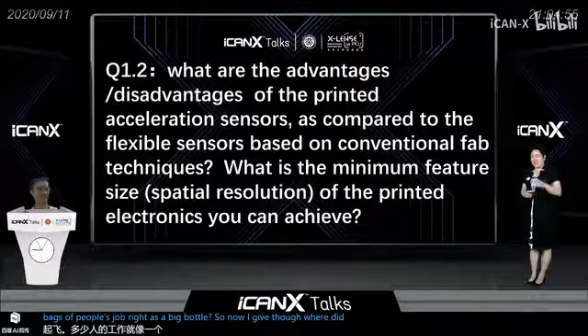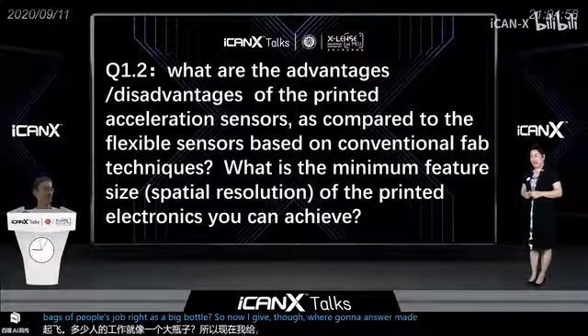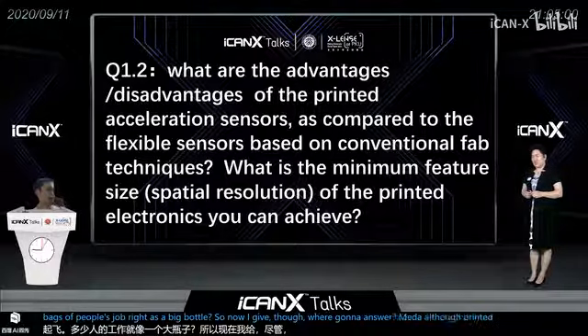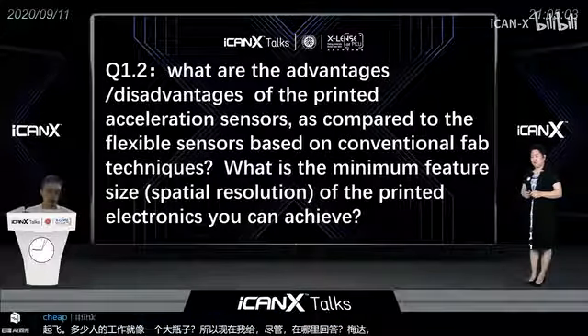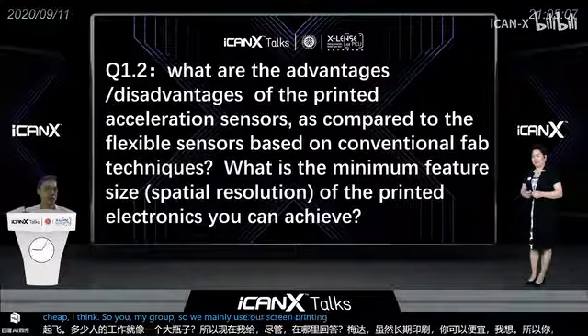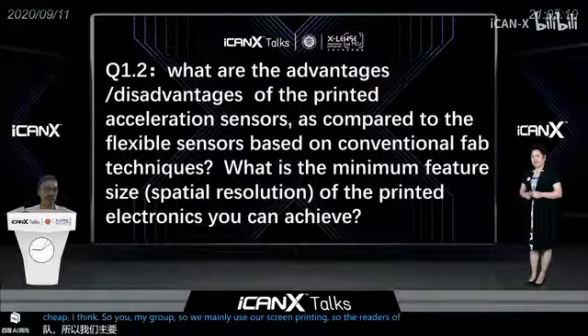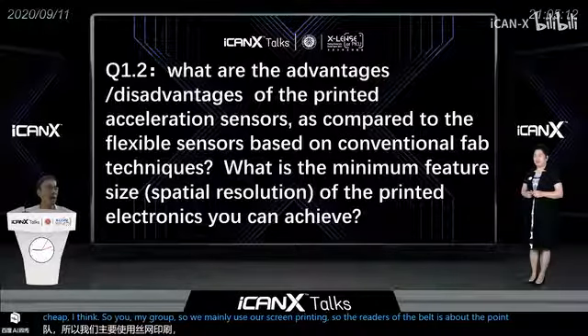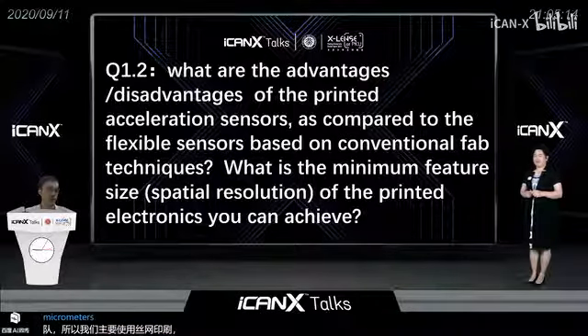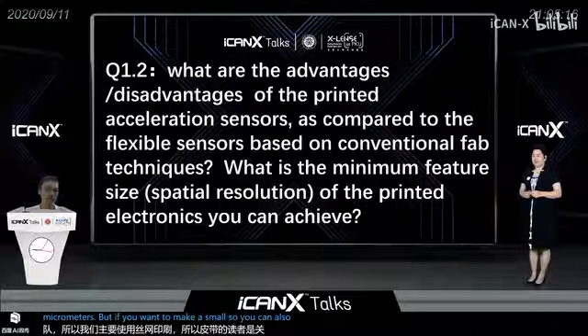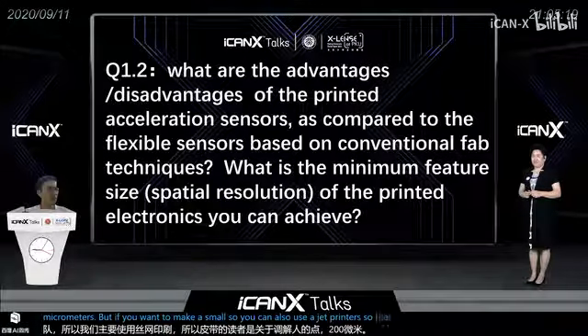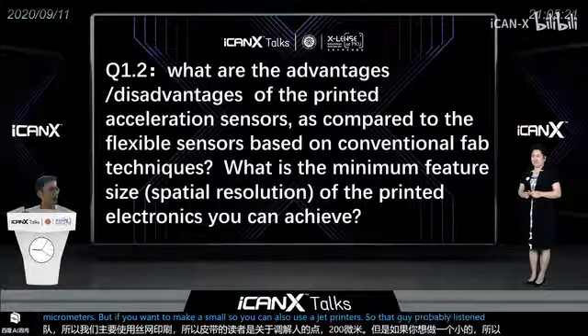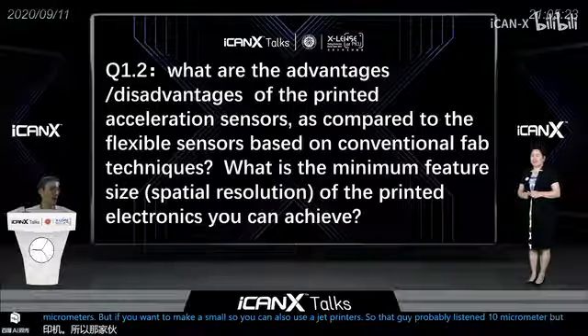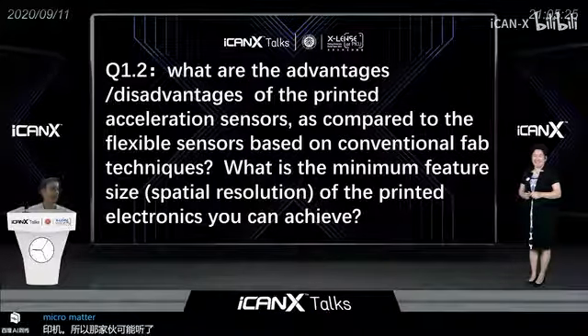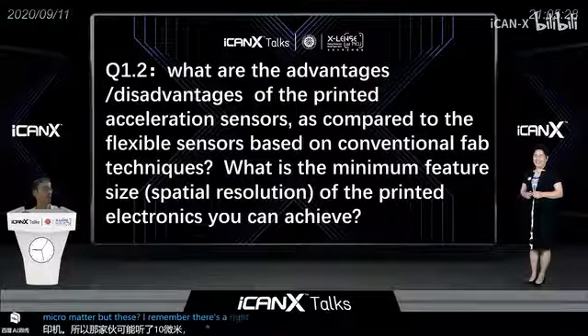So what's the minimal size for the printed electronics you can achieve? Actually, in my group we mainly use screen printing, so the line width of the pattern is about 0.2 millimeter, 200 micrometers. But if you want to make it smaller, you can also use an inkjet printer, which can realize probably less than 10 micrometers, but of course more than a micrometer. That is the minimum resolution people can realize right now.